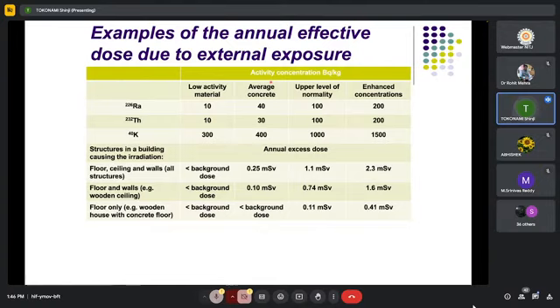At average concrete, average value, in this case, floor, ceiling, and walls contains this radioactivity. It gives 0.25 millisievert per year. Floor and walls, 0.1 millisievert. Floor only, less than background dose. If we take radioactivities with these values, when we calculate annual excess dose, floor, ceiling, and walls gives 1.1 millisievert. Floor and walls gives 0.74 millisievert. Floor only is 0.11 millisievert.